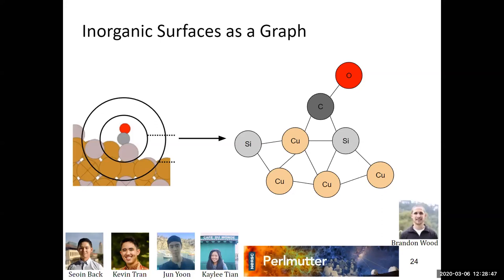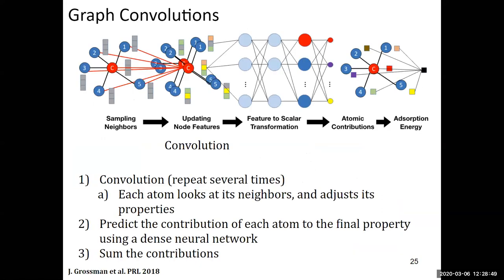Okay, so we have this graph, and we need to turn this into a vector problem, a standard nonlinear regression one. And so the way that you can do that is with graph convolutions, which are a new class of methods in machine learning. You define an operation where every atom looks at its neighbors and it tries to mix the neighbors' properties with itself and update itself. So if I was that carbon, I look at all the things I'm bound to, like the oxygen and two coppers or whatever, and I try and mix those things together. I do that a few times, and then I try and get each one of these atoms to make a guess on the total contribution to the adsorption energy, and then I average or sum all those things together in one final pooling operation. Fairly standard approach.